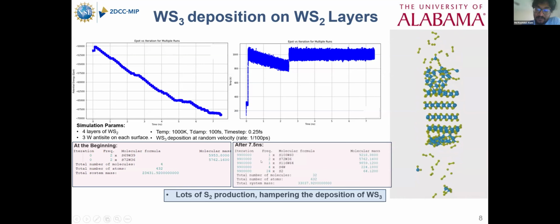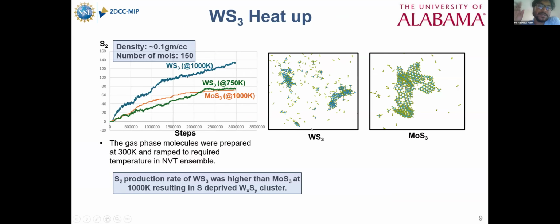We can see that after 7.5 nanoseconds there were about 24 S2 gases, which was not seen in the molybdenum case. In our case, we also see some clusters instead of a proper layer. So the question is, are the sulfur molecules coming from the gas phase species, or are they actually coming from the substrate layer itself? To understand that, we did another kind of simulation.